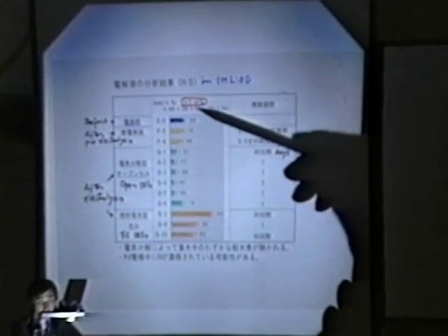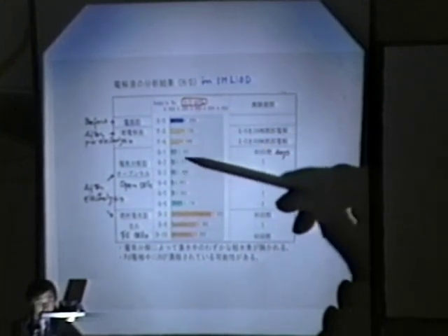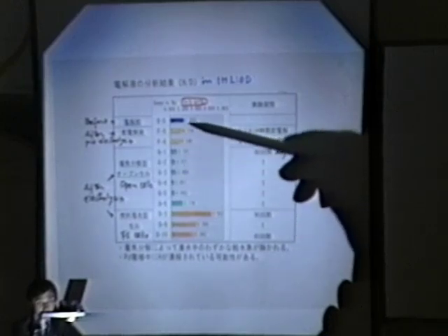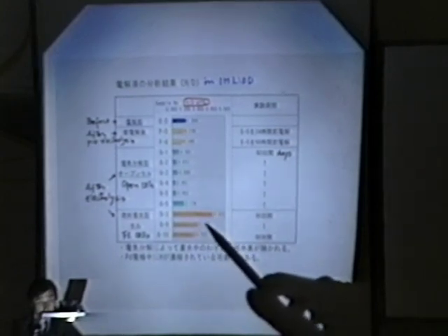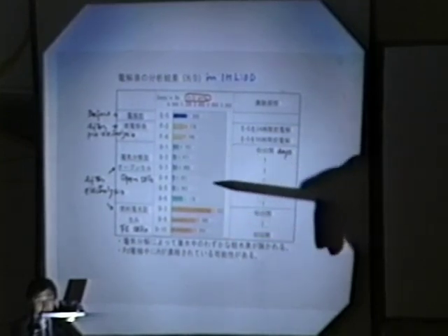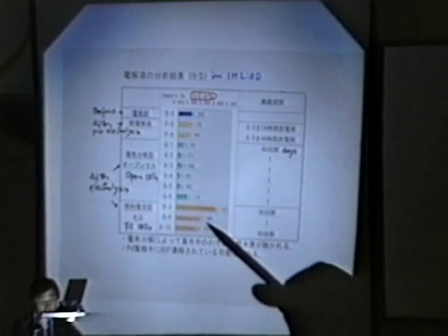It's very clear that in open cell systems, the hydrogen to deuterium ratio becomes very small, much smaller than the original value, because hydrogen is preferentially eliminated from the system, as it is an open system. But for the fuel cell system, which is a closed system, the hydrogen content is much larger than in the open cell system. So the difference between the open cell and the fuel cell systems is not due to this difference of isotopic purity. If it were, the fuel cell system should give a higher loading ratio than the open cell systems.